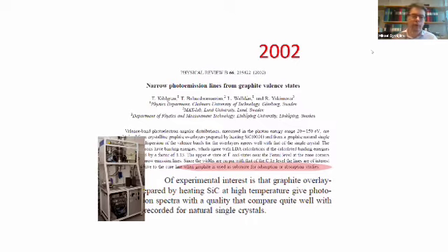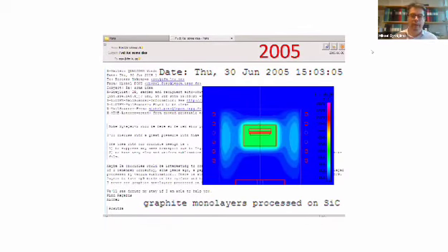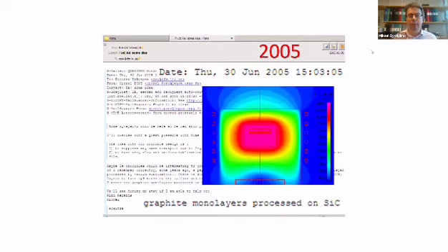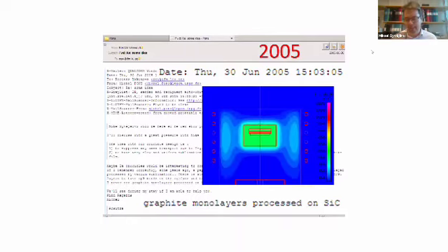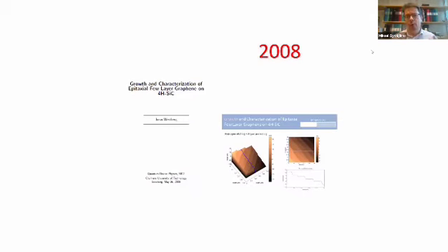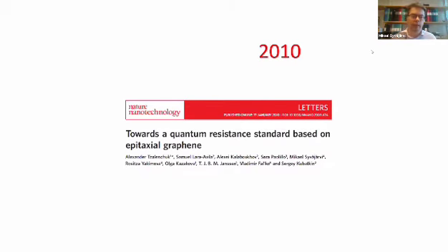When we made these thick graphitic layers thinner, then actually in 2005, we had one layer of carbon on the silicon carbide. So that was graphene. We did not really understand what it was or what it could be good for, but from the growth point of view, it was exciting to do this. Then we tried to control this, and we had some master students working on these things. And in 2010, we could control this in a nice way. There was collaboration with Chalmers again, where they demonstrated the quantum Hall effect on our material. It was very good quality material, which showed it's possible to use this for quantum resistance standards and so on. Then there was a joint paper in Nature Nanotechnology. As a grower, it's very difficult to be in such papers because we never have device demonstrators, so this was a very nice time. That was now 10 years ago.